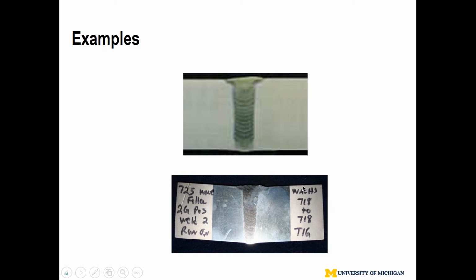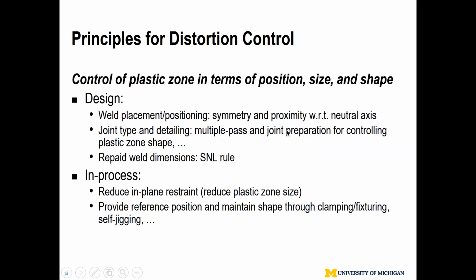Okay, so this is a narrow groove weld from one of the major utility companies for pressure vessel fabrication. You can see we don't need to do measurement. You know this one, because the plastic zone is roughly proportional to the fusion zone, so it gives you strong, very severe angular distortion. This is a narrow gap with good clamping after welding, and you can see virtually no distortion, right?